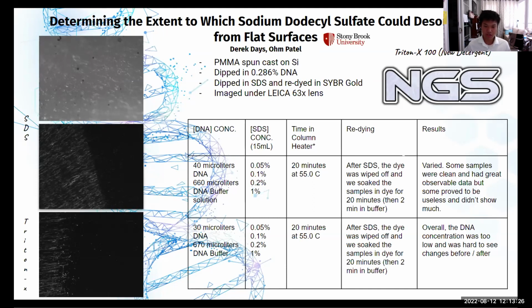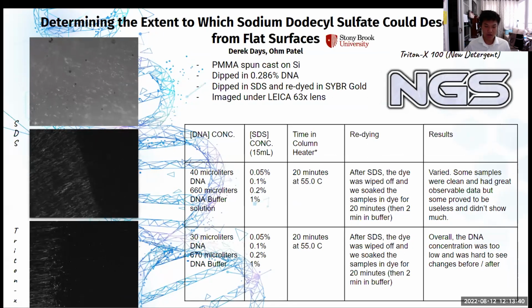The sample surface used was polymethyl methacrylate, or PMMA, spun cast onto a silicon wafer. This wafer was then dipped into a 0.286% DNA solution, also containing dye, and then half of the wafer was dipped into SDS and re-dyed again. Finally, the wafer was submerged in a DNA buffer to make the surface hydrophobic. The resulting surface was imaged under a Leica 63x magnification lens.